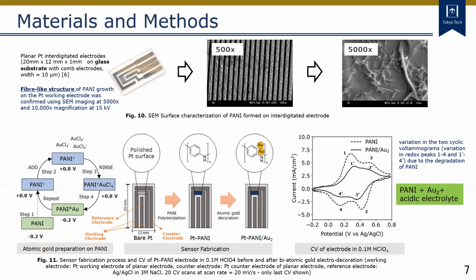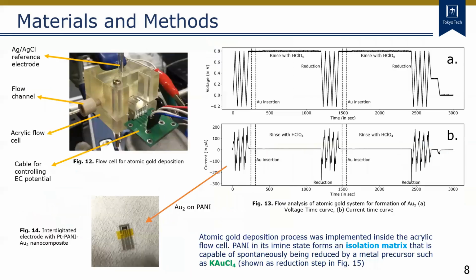There is variation in the voltammogram after PANI-Au2 formation due to the degradation of PANI. The atomic gold decoration of polyaniline was implemented inside a flow cell as shown in figure 12. The voltage-time and current-time response of controlled growth of biatomic gold on PANI, or PANI-Au2, is shown